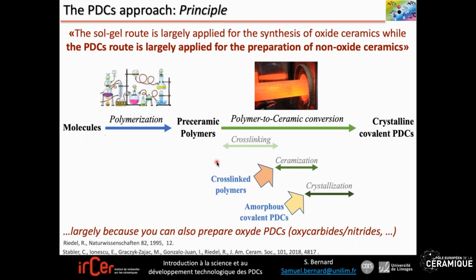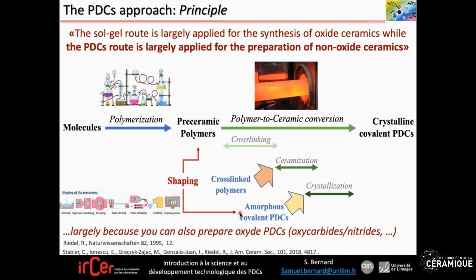So I would say that until now, the process is relatively close to conventional processing. But the main interest of this approach is that you can shape your polymer before the heat treatment using conventional shaping processes, spinning, coating, pressing, injection molding, and form a large range of ceramics after pyrolysis in the shape you have imposed at the polymer level. In parallel, you can shape the ceramic obtained by the direct pyrolysis of your polymer once prepared, in particular in its amorphous state, as is applied in the conventional way. However, this route is really interesting if the polymer-derived ceramic route can provide added value compared to the more conventional way. So we will see later how we can add value compared to the conventional way of preparing ceramics.